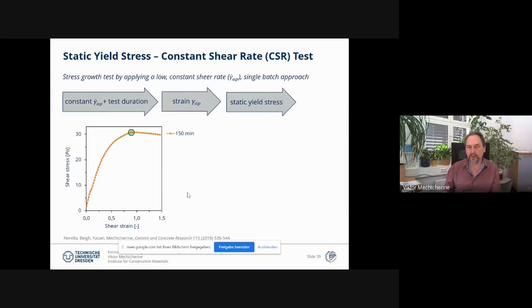Testing static yield stress, and we are talking here really about static yield stress. It means we start such characterization of material with a shear strain rate equal to 0, and then provide some constant shear rate and look at the development of the shear stress with the increase in shear strain. And then we get some response which looks similar to what we also get in mechanical testing of hardened concrete, however, of course, on a very low level. We're talking here about a couple of dozens of Pascal or even less.